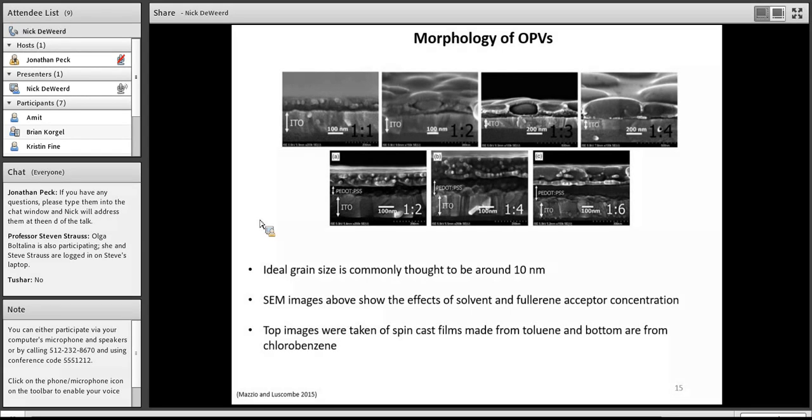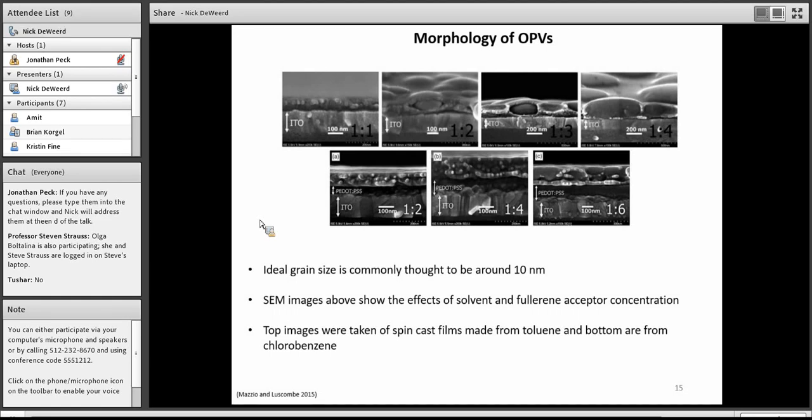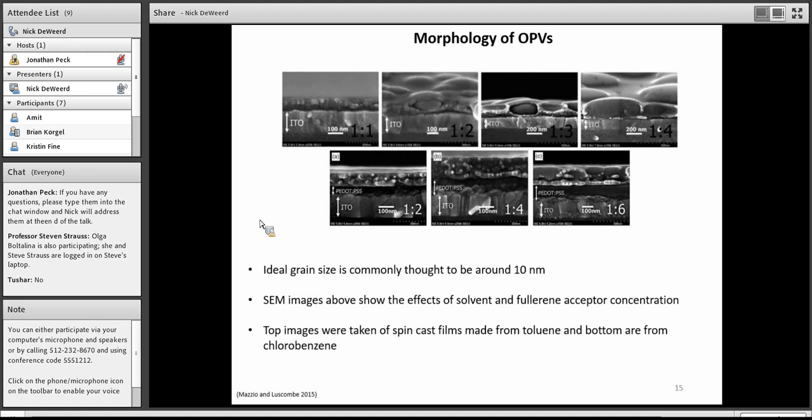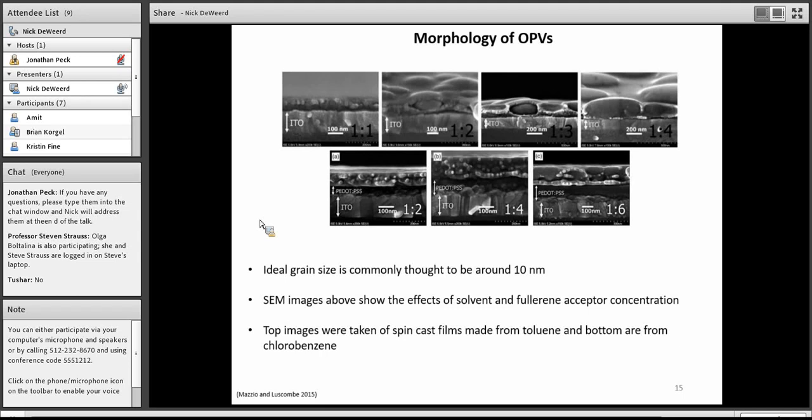You can look at the bottom three SEM images. You can see the fullerene concentration is increasing a lot, but those were deposited in chlorobenzene, which most fullerene have a much higher solubility in than toluene. You can see the grain size is visibly much smaller compared to what you get in the toluene deposited layer. And that's just for spin-casting, which is really only a lab scale technique predominantly. These are just a couple variables. Morphology gets much more complicated than that. You can talk about adding in additives like diiodo-octane in order to decrease these aggregates. You can also talk about annealing the films to change the morphology. So there's a lot of variables that can be adjusted. And when you're optimizing these OPV devices, these are all variables that have to be considered.